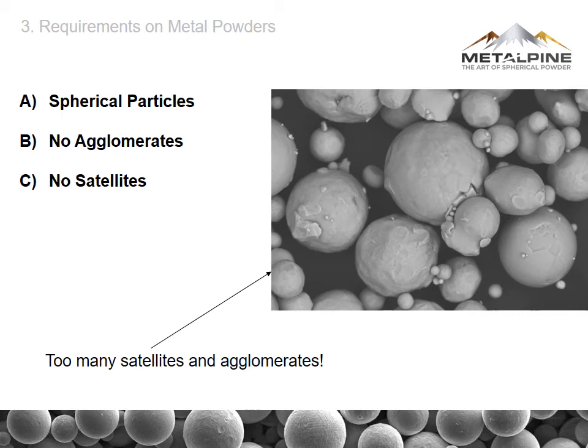And you see also a lot of satellites in this picture here. Imagine these small particles. When the laser goes over this small particle, it will immediately evaporate and also increase the probability of defects in the printed part.